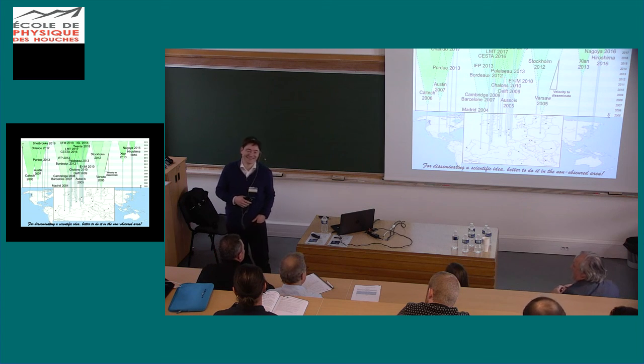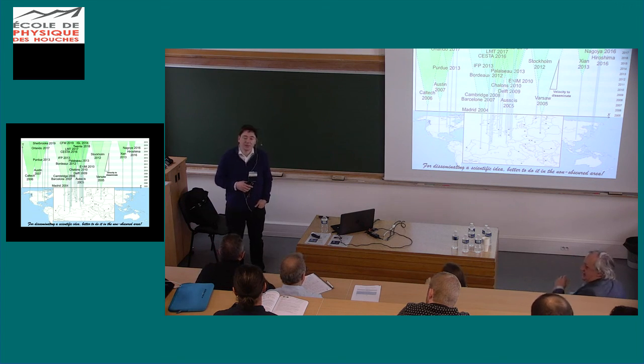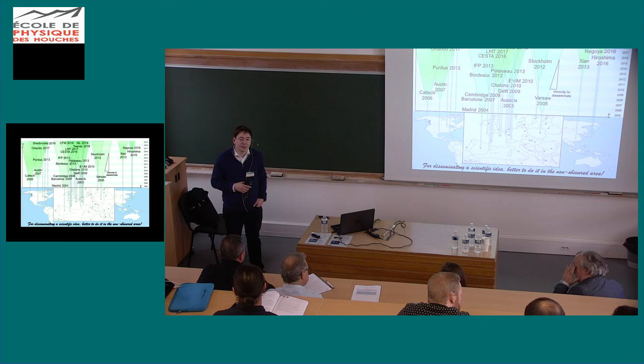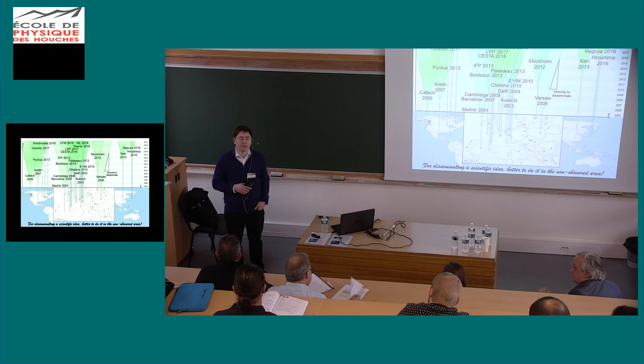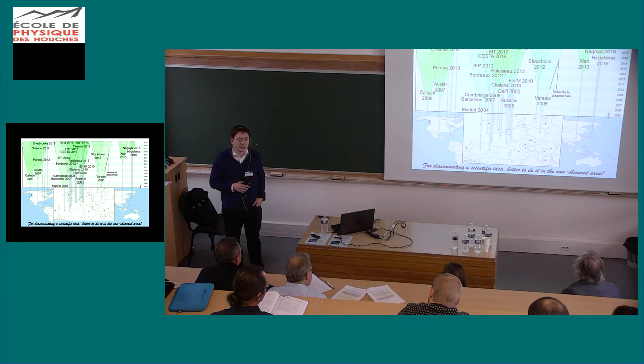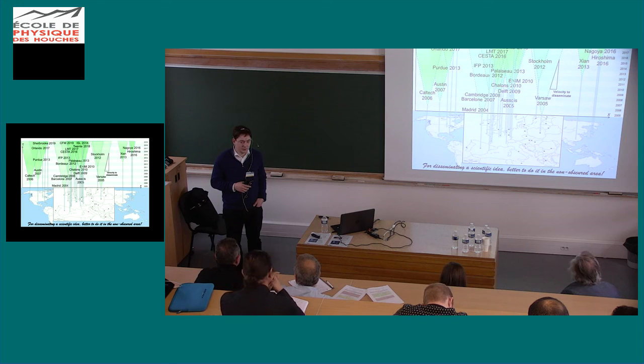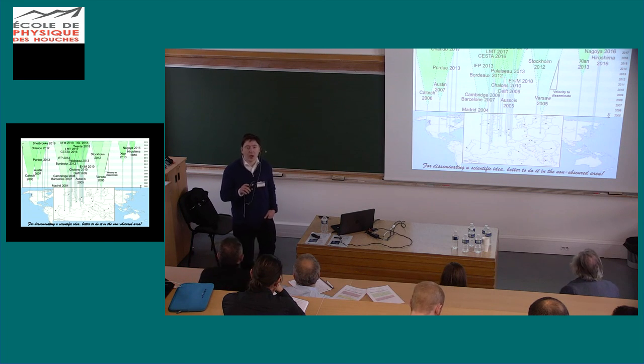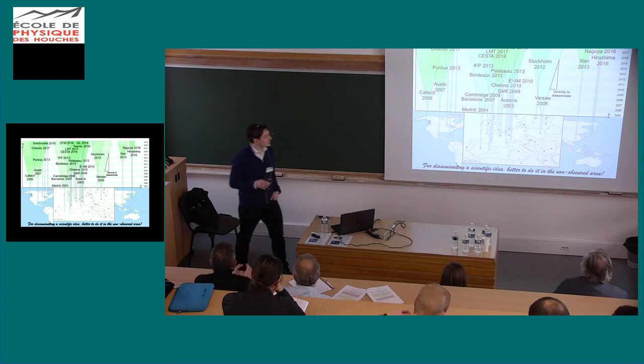Thank you. In your compression test of 1918, you told us that the propagation of the cracks is due to tensile stress. But don't you think that nucleation is driven by a mode 2 initial crack, by shear stress, and then propagation by tensile drive? In which case, pardon? Uniaxial compression. Ah, uniaxial. Okay, uniaxial is